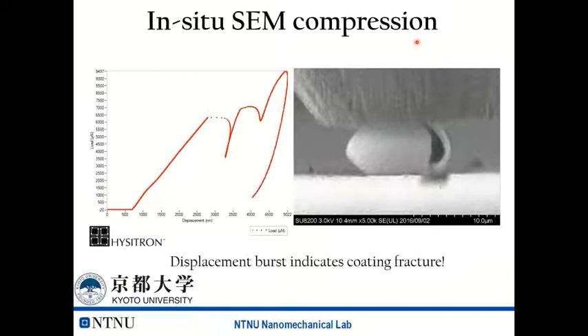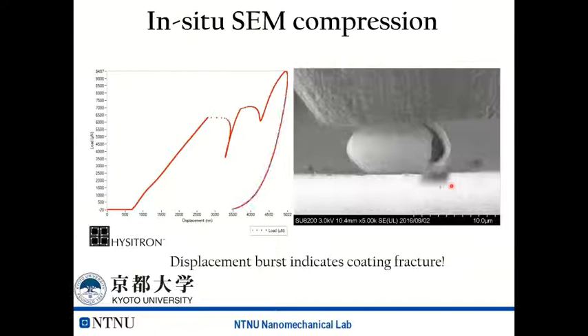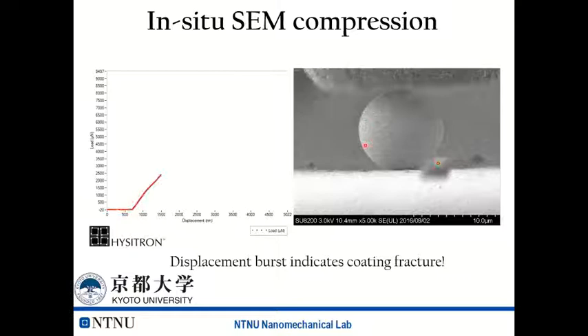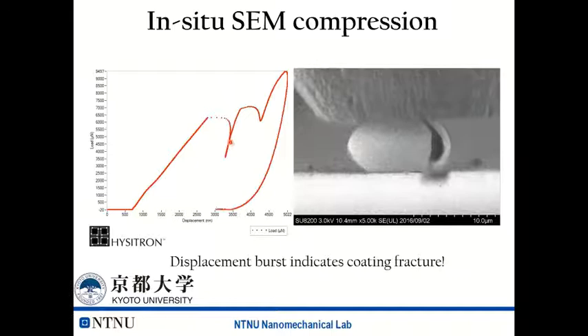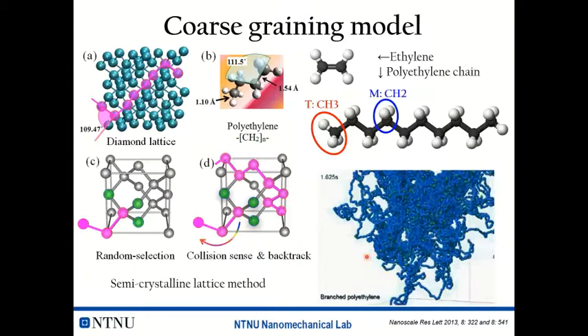Later, we carried out compression inside the scanning electron microscope by collaboration with a partner university, so we can easily observe what happened to the particles during deformation. We can see that several cracks — one here and another on the back — occurred on the metal coating, and that corresponds to each displacement burst. This confirms the deformation behavior of the particles.